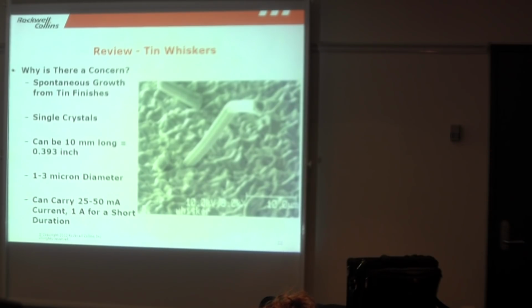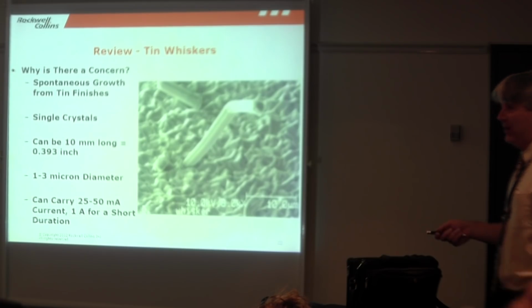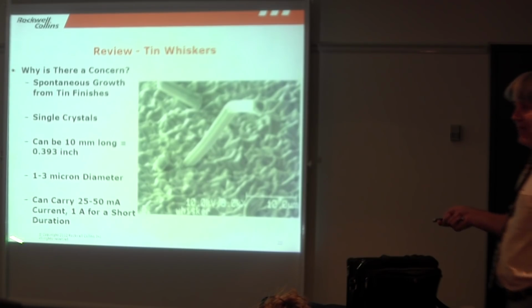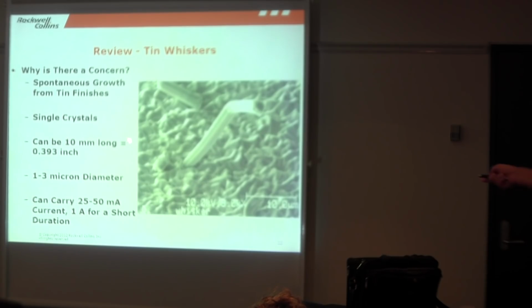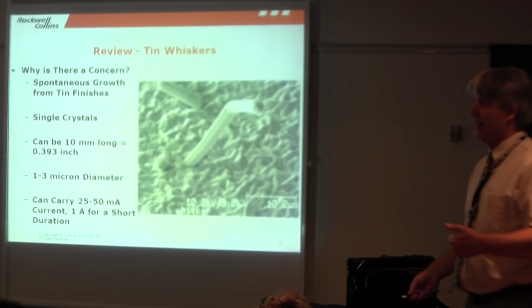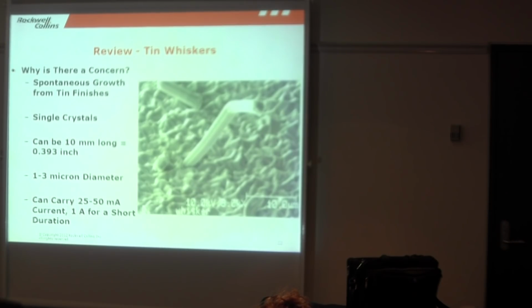Here's where we're going to. I'm going to start at the bottom, not at the top. The industry data has reported that a whisker can carry from 25 to 50 milliamps, and 1 amp for a short time. I'm not a double E. I don't speak Sparky very well, but my double E buddies say that's a problem. That's pretty good. In some circuits, that's an issue, and not good. And typically 10 millimeters. I've seen them a lot longer, a lot shorter, but in a lot of the data centers around, they can be as long as 10 millimeters. I know that's a problem. I can see that looking at my circuitry and stuff.